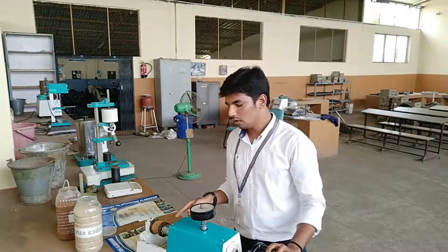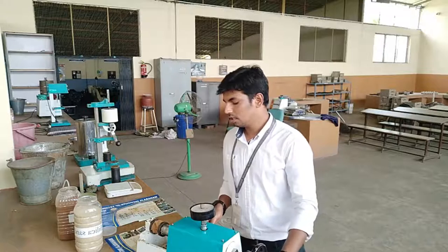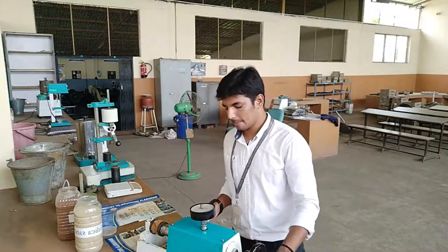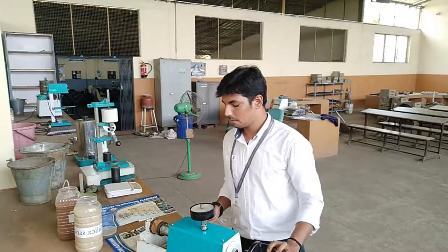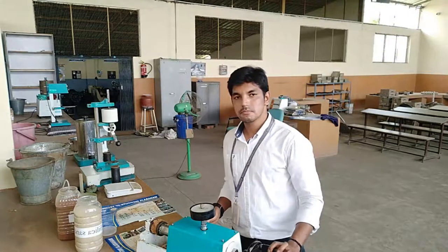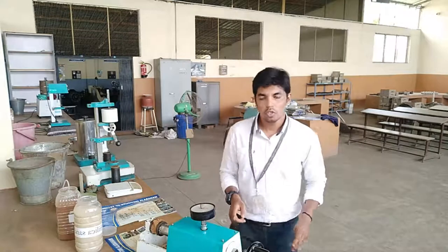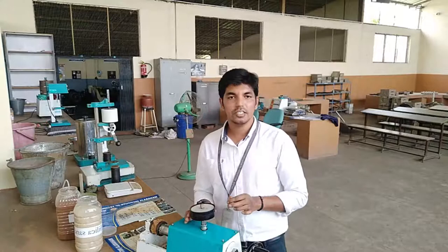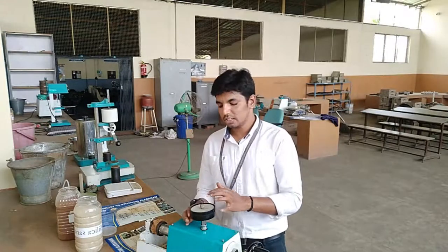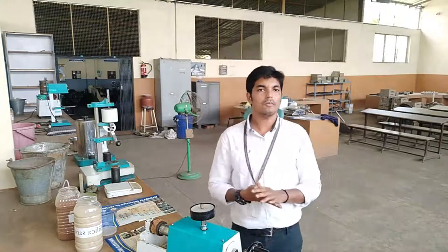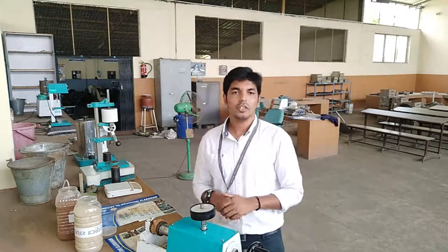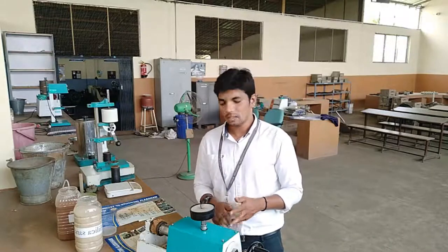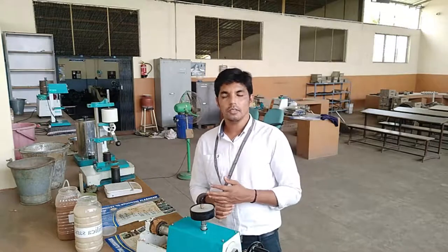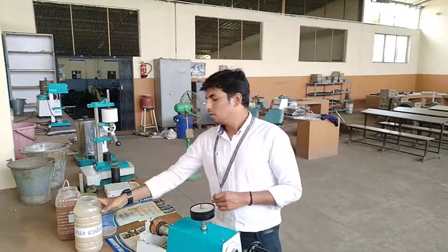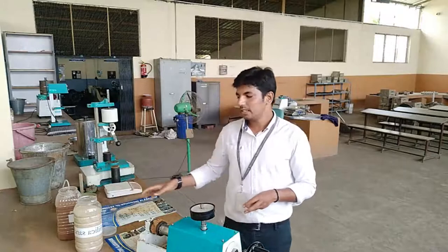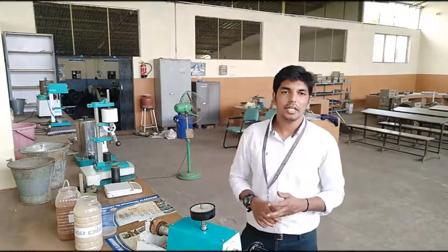Observe now, the specimen is undergoing compression and now it is undergoing shear. So now note down the dial gauge reading in the shear scale. Initially I set it to 36, it has shifted from 36 to 40, that means 0.4. So 0.4 into 100 gives the shear strength in grams per centimeter square. So the shear strength of the given molding sand of 135 grams of silica sand and 15 grams of clay binder plus 12 ml of water is 40 gram per centimeter square.